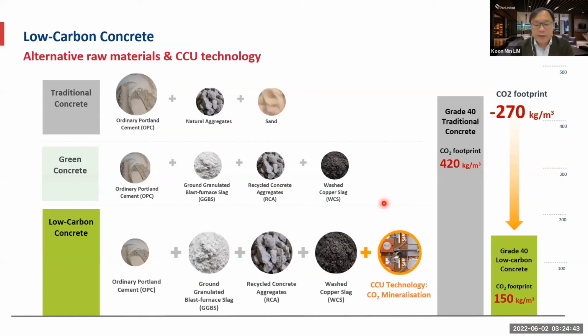So what we can see here, through the replacement of natural aggregates with recycled aggregates and recycled materials, together with CCU, we are able to reduce the carbon footprint from as high as 420 to 150. And that is more than 60% reduction, with 270 kilograms of CO2 per cubic meter being reduced.